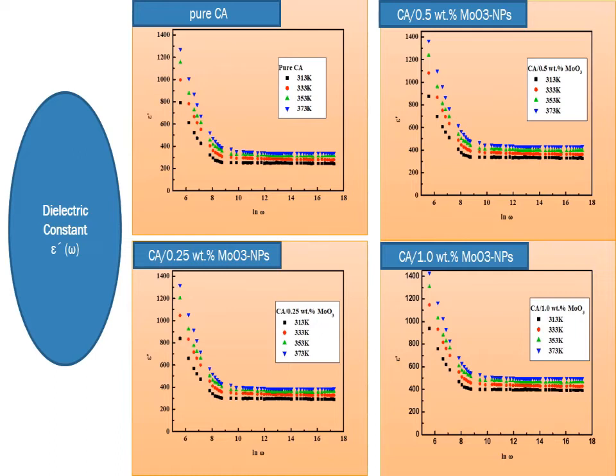Here we draw the dielectric constant as a function of frequency and temperature, and it was observed that the dielectric constant increases with increasing temperature, and also with increasing molybdenum trioxide nanoparticle concentration.